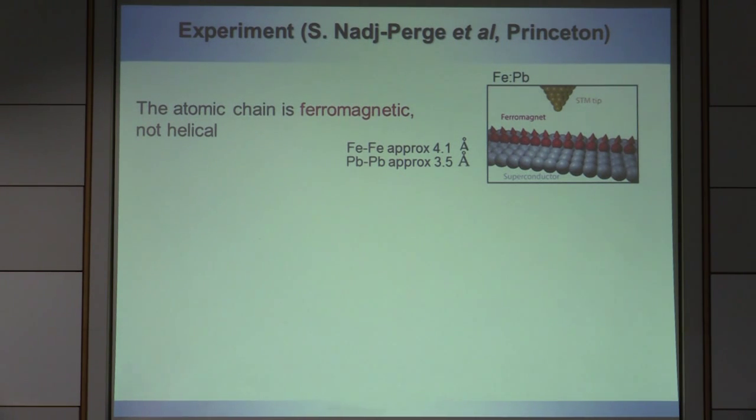So it's not a big deal yet, because as we discussed, if there is spin-orbit interaction, then having a homogeneous magnetic field is not so bad. Now, lead is a heavy element, so atomic spin-orbit is strong. And on top of that, of course, in the bulk, lead, as essentially any metal, the elementary cell has inversion symmetry, so spin-orbit is kind of cancelled. But at the surface, the inversion is broken. So there is a Rashba-type spin-orbit interaction at the surface. So it's not that bad to have ferromagnetic ordering. That doesn't kill the idea of an interior topological state.